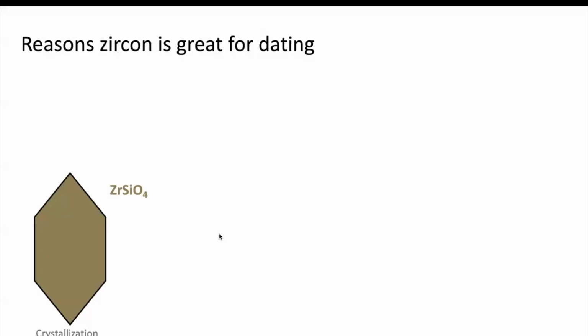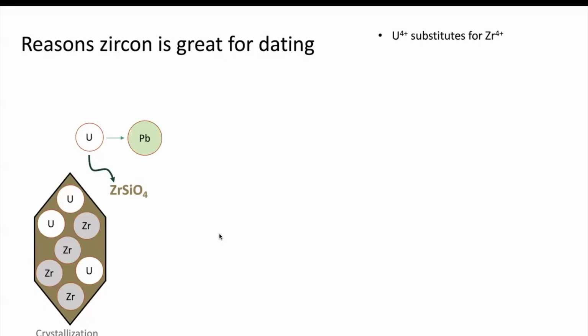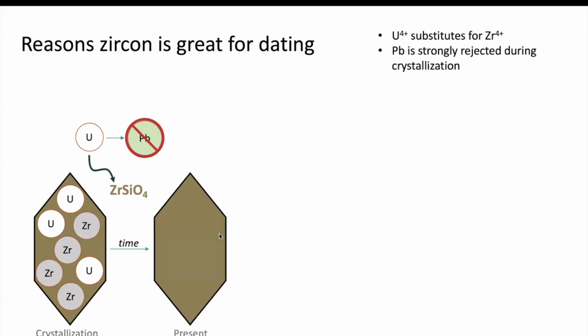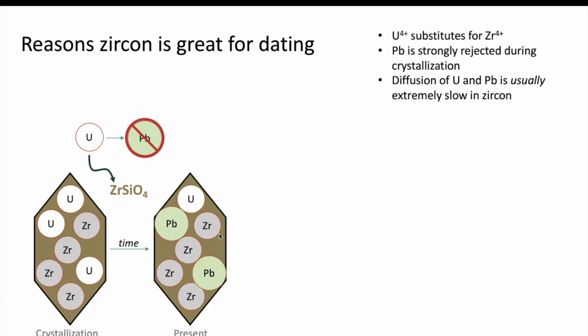There are some good reasons why people use zircon for uranium lead dating. Under typical geologic circumstances, it does a pretty good job. So uranium directly substitutes for zirconium when zircon crystallizes out of a magma, but zircon strongly rejects lead. Over time, the uranium breaks down to lead, and barring unusual circumstances, the diffusion for both uranium and lead through zircon's crystalline lattice is exceedingly slow. The closure temperature of this system is quite high. It's about 900 degrees centigrade. This means that zircon can lock in an age when it passes below that temperature as it's cooling.